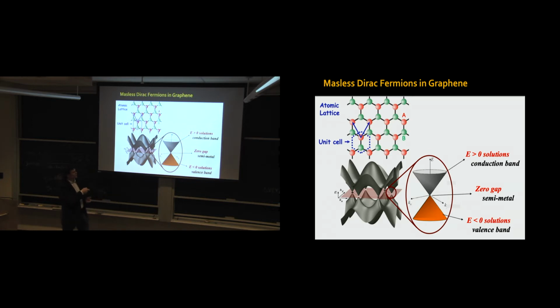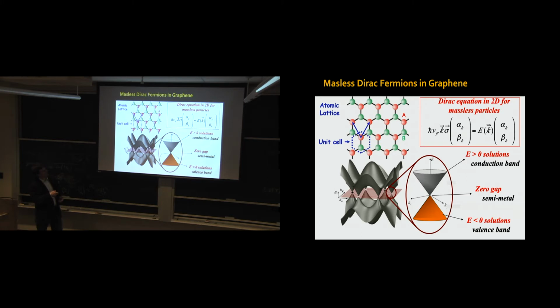This is the same dispersion that you have for photons, except that, of course, electrons in graphene are fermions. In fact, this energy-momentum dispersion is captured by an equation which is nothing else but the Dirac equation in 2 dimensions for massless particles. Energy is linear in momentum. This spinor in the Dirac equation usually represents spin up and spin down of the electron. In the case of graphene, this is a pseudo-spin, which tells you whether the weight of your electron wave function is on the A sublattice or on the B sublattice.